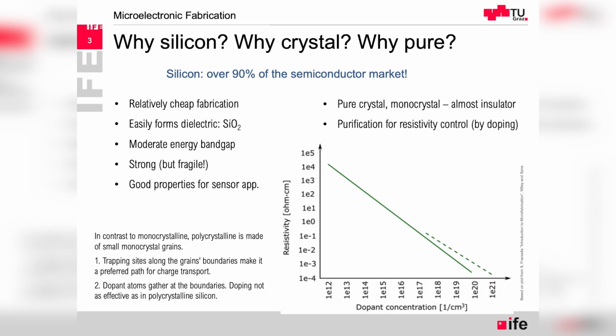Then it is relatively cheap in fabrication. We can create wafers of silicon to quite large areas, in contrast to other semiconductors where the wafers will be much smaller. We have for free a dielectric, which easily forms. If we do nothing, actually it forms silicon dioxide. So if we want to make a MOSFET transistor, it's relatively easy to make the gate oxide. It's only the art of making it accurately controlled, because for a gate of a few nanometers, we really have to do it very slowly to know that all the transistors will have the same gate thickness with just a small margin of uncertainty.